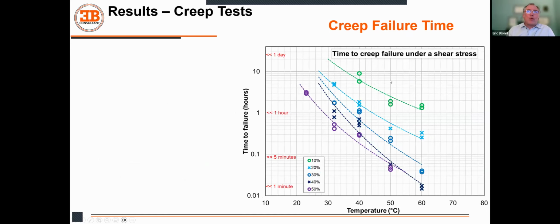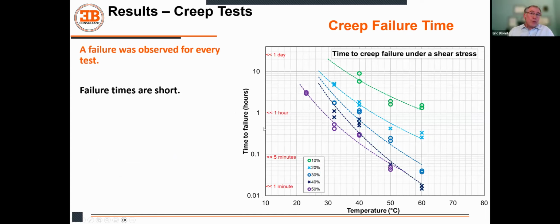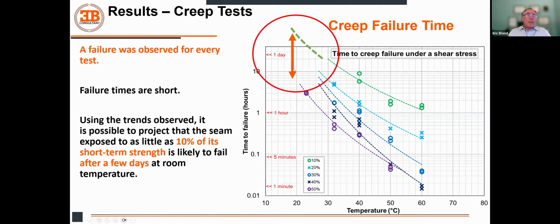We looked at the time to creep failure under the various shear stress, and we found that first, the time to failure were very short. So the green curve you have on top here is 10% of the shear strength of the seam at the test temperature. So that can be here, as I showed you before, it's already about 15% of the seam strength. So we are very, very low. And we see that the failure times are pretty much very, very low. They are in days, if not hours, if not minutes.